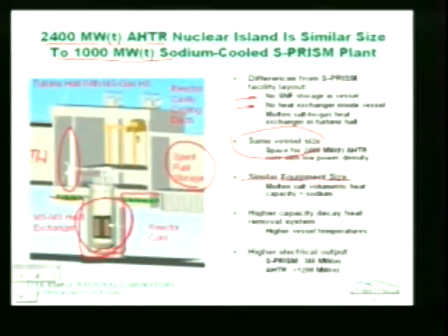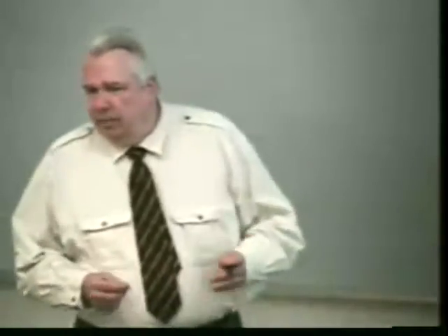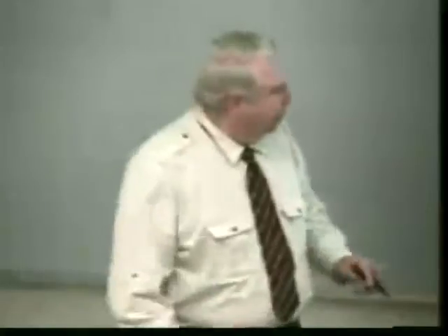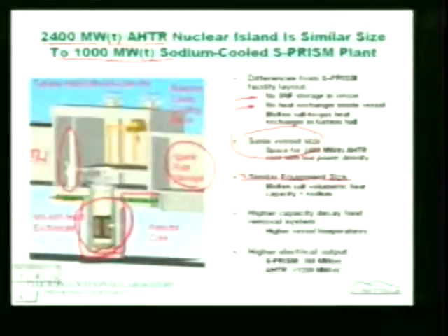As I showed in an earlier curve, molten salts are about 4 times better than sodium for moving heat around. Translated, the equipment size shrinks by a factor of 4, except we're working at a little bit higher power level. But with a better coolant, we can put more reactor, more facility in the same plant. We changed the heat decay cooling system, which I will describe later, and we went to much higher temperatures, which means much higher efficiency of the reactor.